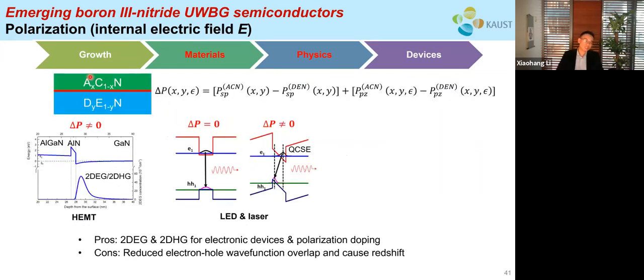So let's use the heterojunction as an example. Again, a heterojunction is when you put two semiconductor layers against each other, right? So let's say we have two layers, which are AC nitride and DE nitride, and ACDE can be from any of the group 3 elements, such as boron, aluminum, gallium, indium. So when they have formed this heterojunction, there will be a polarization charge at the interface. I call it delta P.